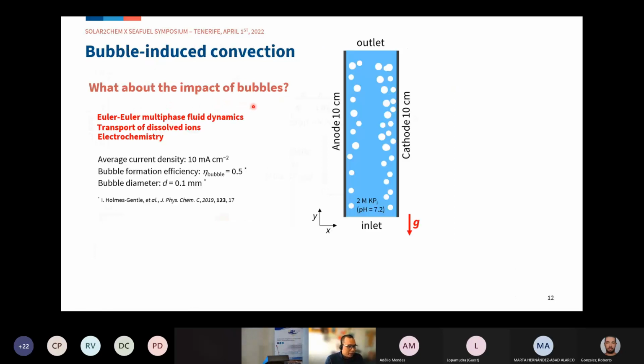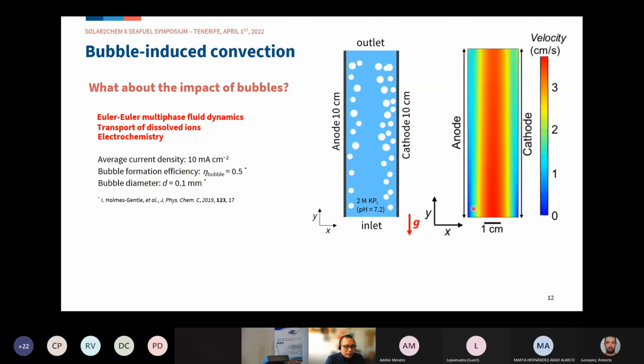Now, what about the impact of bubbles? The experiments or simulations I showed did not consider any bubble formation. We improved that by introducing Euler-Euler multiphase fluid dynamics and introducing bubbles into our system. We take the same level of current density, but the bubble formation efficiency and diameter are assumed constant, based on an experimental report in the literature. The results are shown here.